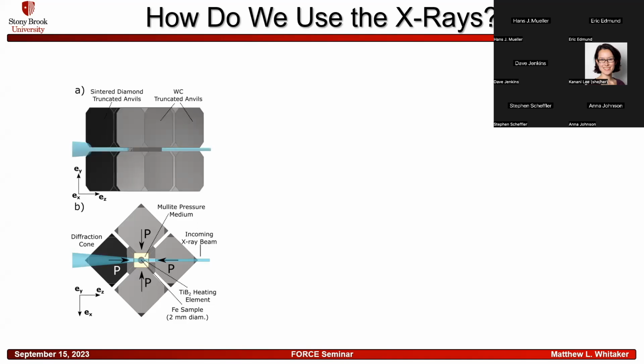You can see here that the X-ray beam is actually shot in between the anvils. So it goes right in between the anvils to be able to hit the sample. And then we get the information out the backside by sending the diffracted beam through sintered diamond anvils, which are transparent to the X-rays, as opposed to the tungsten carbide anvils that we use on the front side that just eat all of the X-rays up.